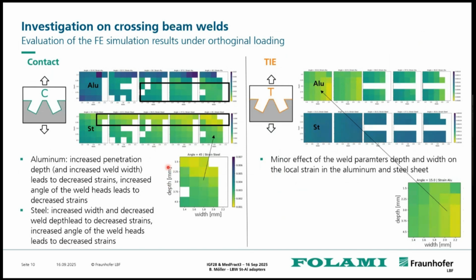So we have the depth of the weld geometry, we have the width of the weld geometry, and we have the angle, which could be varied. And we see in color the strains resulting from the finite element simulation. So dark blue is higher strains, green and light yellow is lower strains, which give us the first information in which configurations beneficial weld geometries result, so that we can say increased penetration depth leads to decreased strains, for example, and an increased angle to a certain amount also leads to decreased strains.